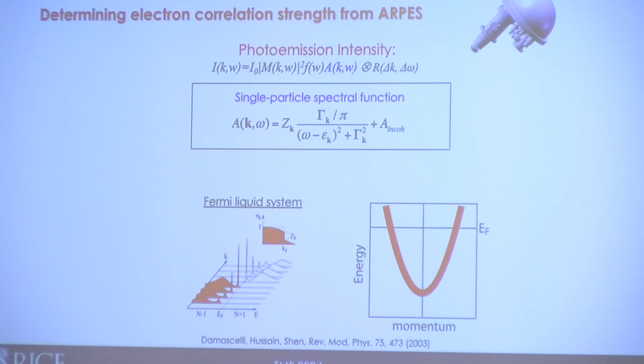If you start to consider interaction on the single particle spectral function, for example, in a Fermi liquid, what would happen is that you can rewrite this into two terms. There will be a part that looks almost like the non-interacting limit. These are the quasi-particles near the Fermi level with some modifications. And then there's another term, which is the incoherent part, that gets pushed farther away from the Fermi level, right? So from a spectral perspective, what do we see? We will see all of this stuff carried essentially simply in this coherence factor, which varies between 0 and 1, and there are two ways in which this modifies the spectra.